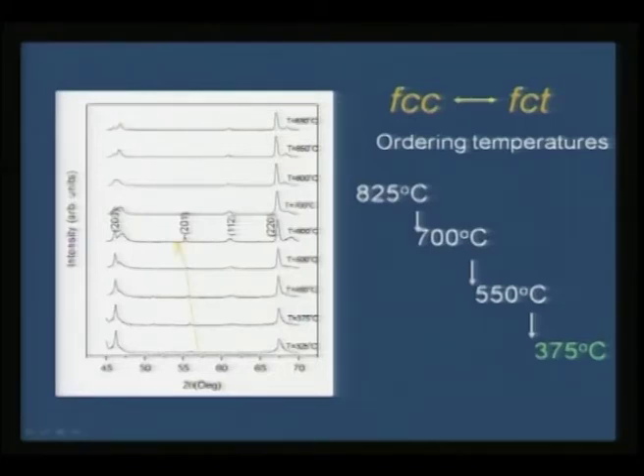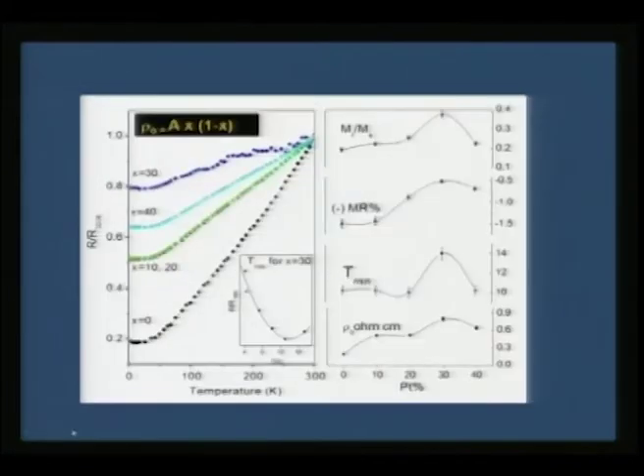Not only that, you can see that this FCC to FCT transformation is occurring as you are going to higher temperature, and this 200 and this 220, incidentally these are the peaks of platinum substrate. This is not the system peak, this is the platinum substrate peak. So what you should be watching is the crystallization or the FCC to FCT transformation which is occurring here as a function of temperature. This is a high temperature X-ray pattern that we have done for cobalt platinum 50-50 alloy. So you can see how the crystallization and phase transformation occurs.